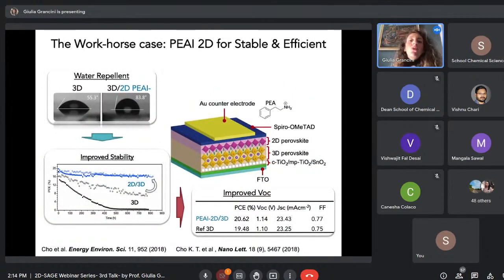Overall, what is the role of this gradient structure? The 2D perovskite on top improves the water repellent character of the surface. You can see here by contact angle, which increases a lot, which in turn leads to an improved stability of this 3D-2D structure with respect to the only 3D. So basically, you are making your device more robust to water humidity, preventing the degradation of the 3D perovskites.